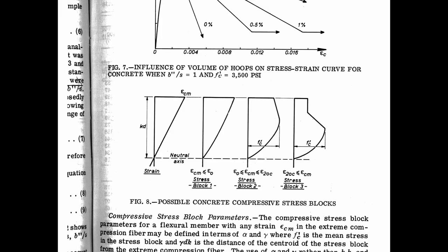Okay, this is the distribution. So in the concrete cross-section, if the stress is low, you might see the linear distribution. This is the strain, but anyway, when the strain is low, the stress and strain are pretty much a linear distribution. And then more and more non-linearities. Okay, over here, that means this point just crosses the strain equals 0.002. So you can see the stress softening. In this zone, it is increasing until you hit 0.002, and then it drops down.